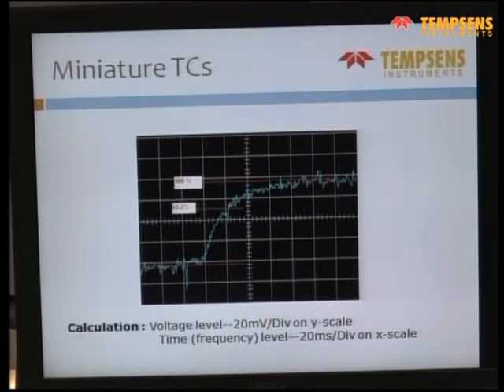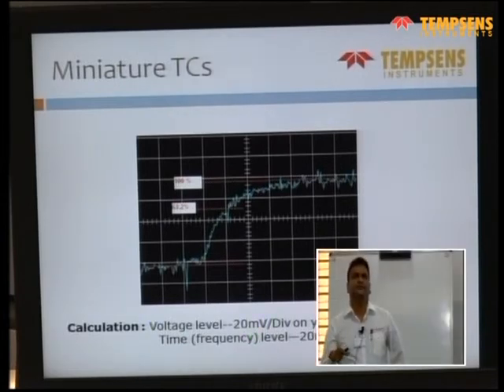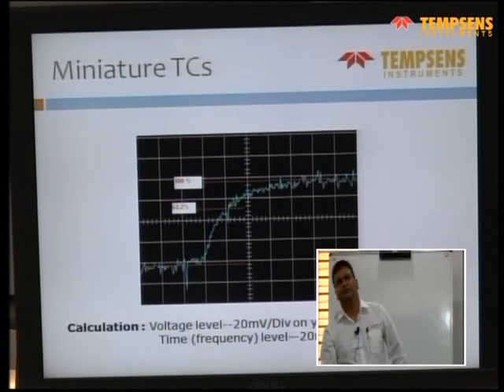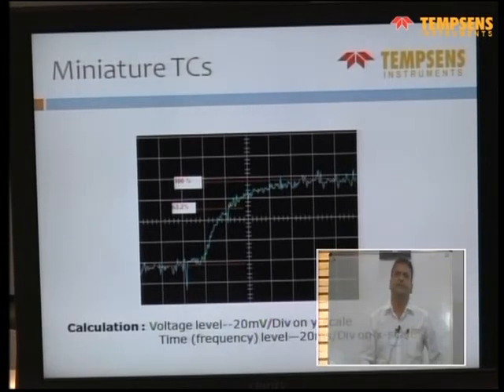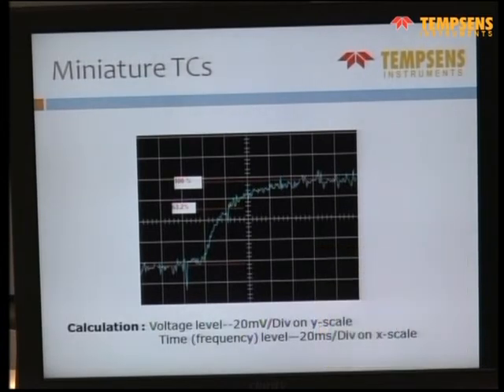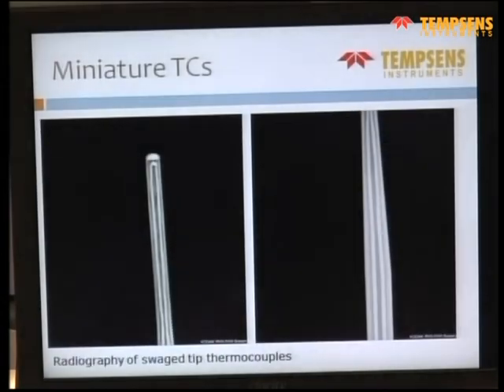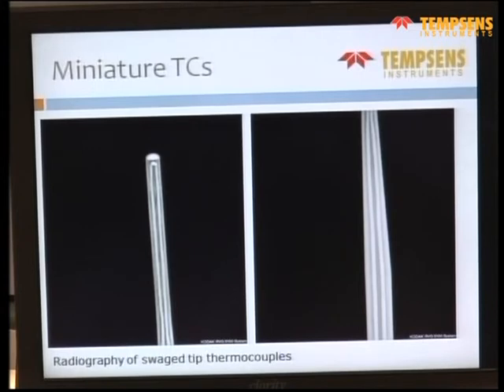So these kinds of things can also be available. Here you can see the response time check that we did for the customer. T63 was about 30 milliseconds, so each T63 was close to about 30 milliseconds. Each division is about 20 milliseconds, and this is a swage thermocouple. You can see it is narrowed from the bottom so that the tip is thinner and the rest of the thermocouple is bigger.